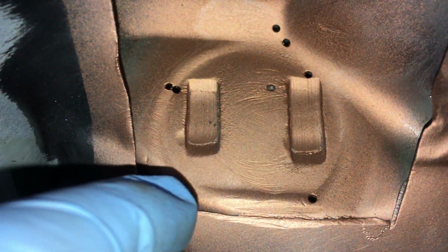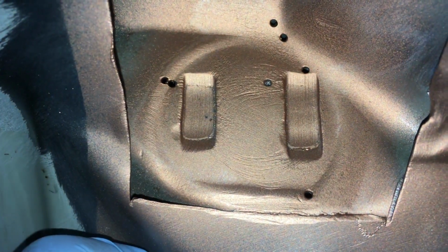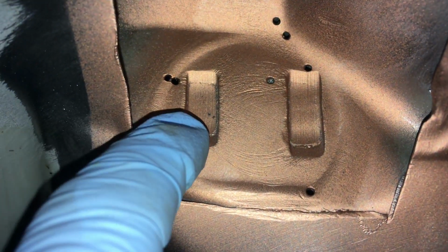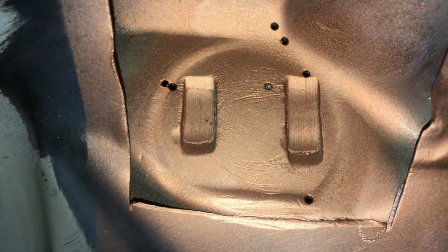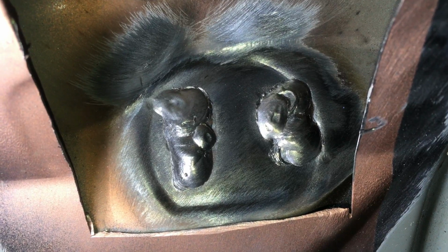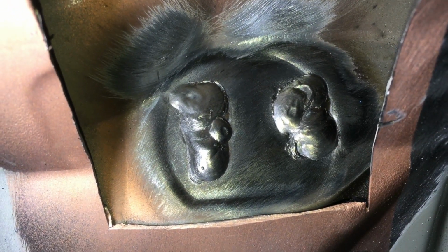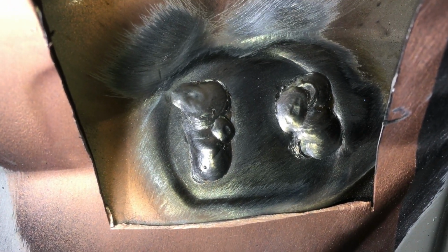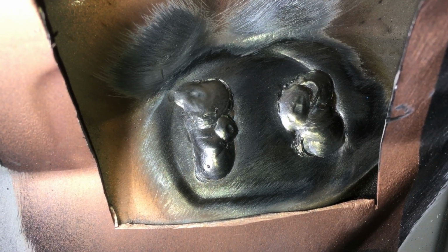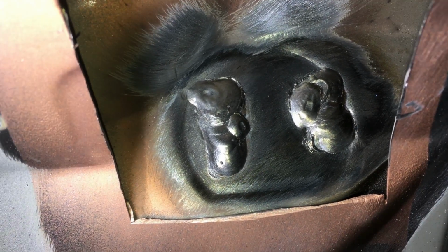Stop drills at the ends of the cracks, two old MIG welds removed, and now we can weld those up as well as welding the cracks. There's the welding complete. We've covered over the crack on this left hand side front mount, and also filled in the areas that we removed the old MIG weld from.